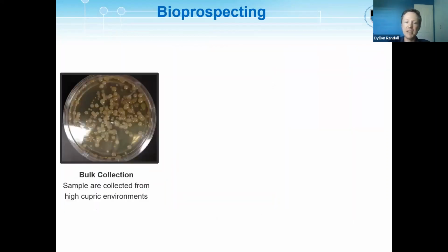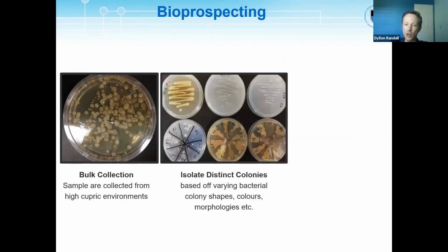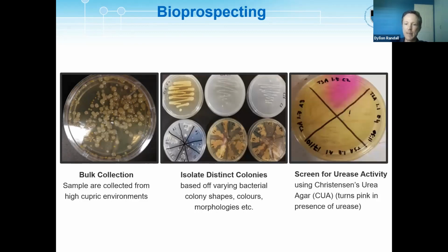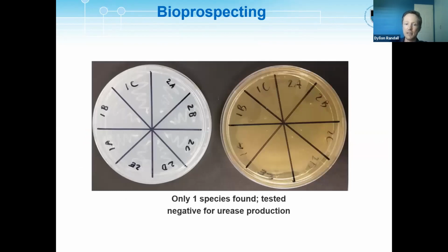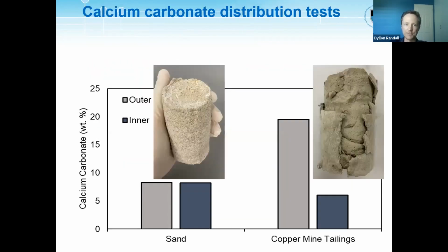So then we moved on to see if we could look for urease producing bacteria in the mine tailings. So we took the mine tailings and did a bulk collection, isolated distinct colonies and looked for different bacteria. And there's a cool technique where you add this material, and if it turns pink, it shows an indication that urease is present. After isolating some bacteria, we found one promising species, but unfortunately it didn't test positive for urease production. But this is something we're going to continue looking at.